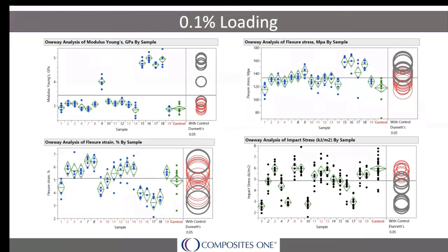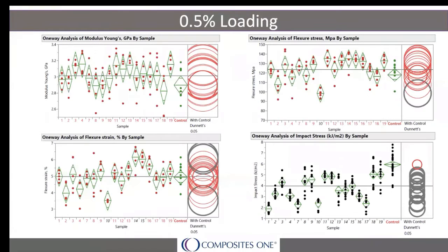All right, so let's take a look at the same type of data for the 0.5% loading. So here are the same 4 graphs for our 0.5% loaded samples. Immediately in the top left graph of flexural modulus, you'll notice none of the samples tested showed any statistically meaningful change from the baseline, and all are in red. You'll notice that the spread of results is larger than the 0.1% loading we showed on the last slide. There is simply too much variation in results to have any confidence in them being different from the baseline.